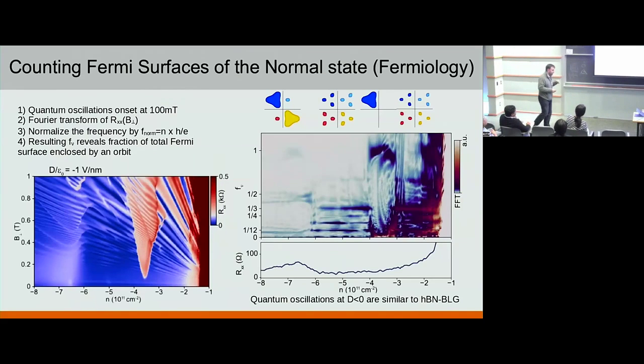Another important point, which sets this system apart from twisted bilayer graphene, where you can have some twist angle disorder, is that here you can gain a lot of insight into the configuration of the Fermi surface by performing Shubnikov-de Haas measurements. You apply a magnetic field, look at the doping density, fix your displacement field, and then you see some oscillations. And the idea is that you follow this procedure where what you get is the output of a Fourier transform. You can get the characteristic frequencies that tell you what fraction of the Fermi surface is occupied by different pockets here.